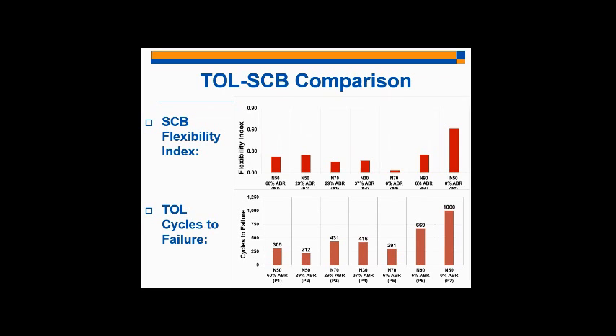And even though there's only 6% ABR in P5, something went wrong basically in the mixing or compaction or production of the mix that we don't know. It's interesting because IDOT's TOL test cycles to failure matched ours. Mix 5 is one of their lowest performing mixtures for a reason that we are not sure of yet. They're conducting forensic studies on this, but it is one of their lowest performing mixtures and one of our lowest performing mixtures.